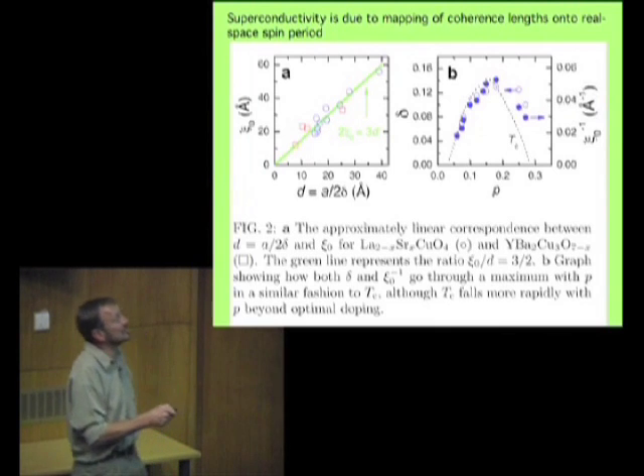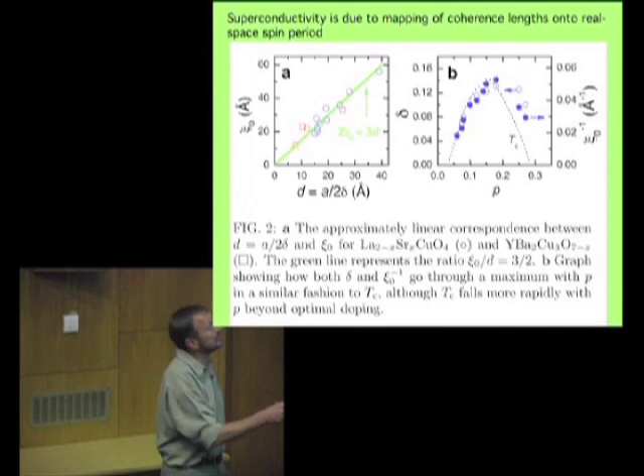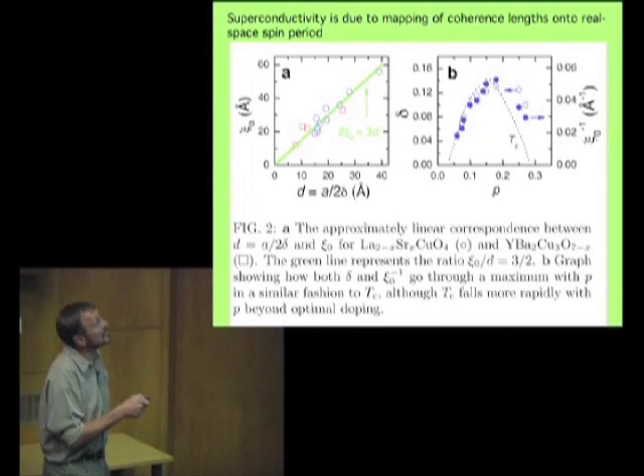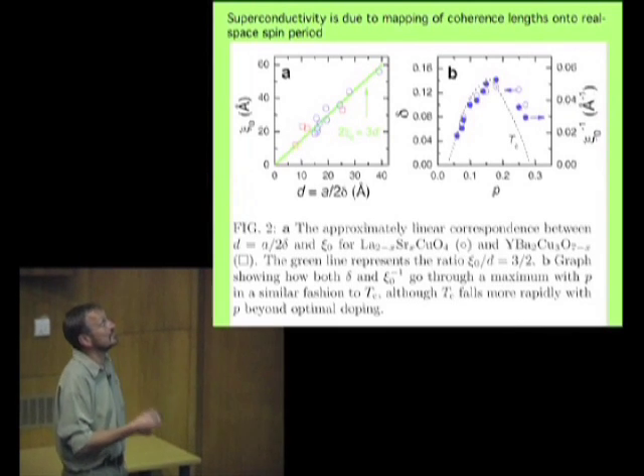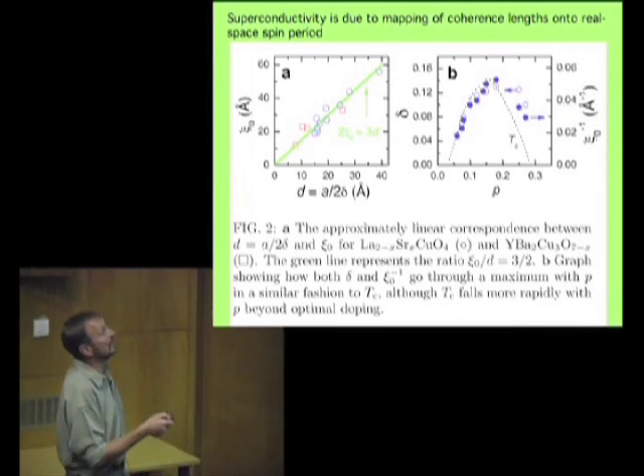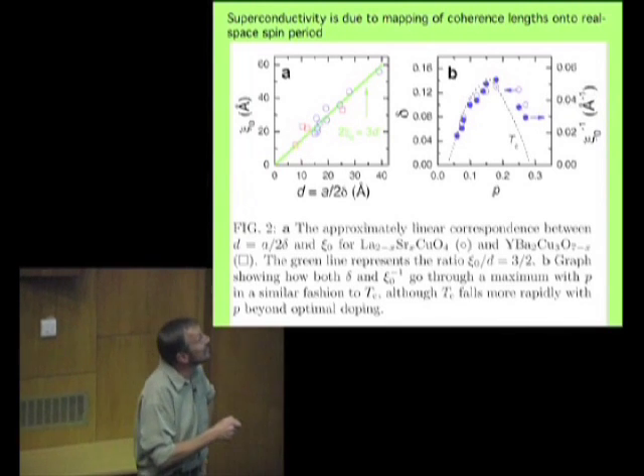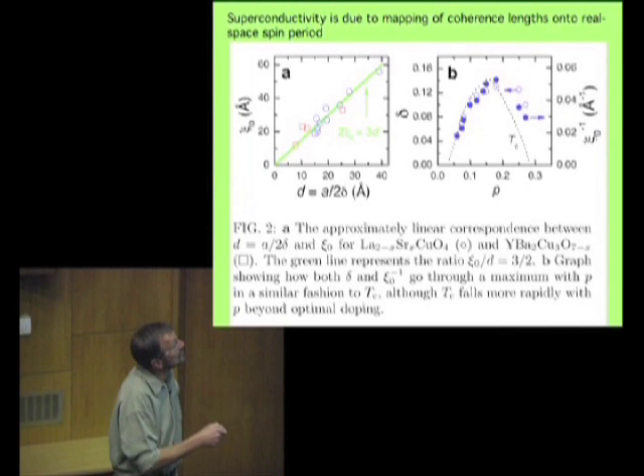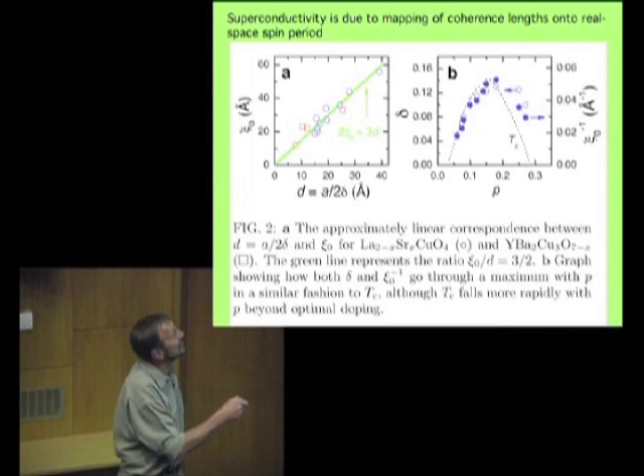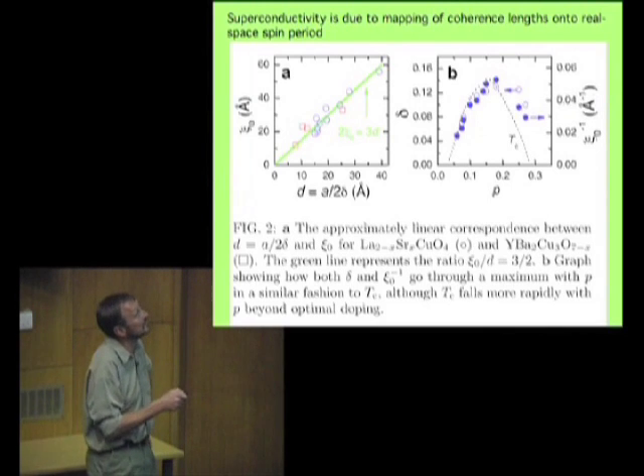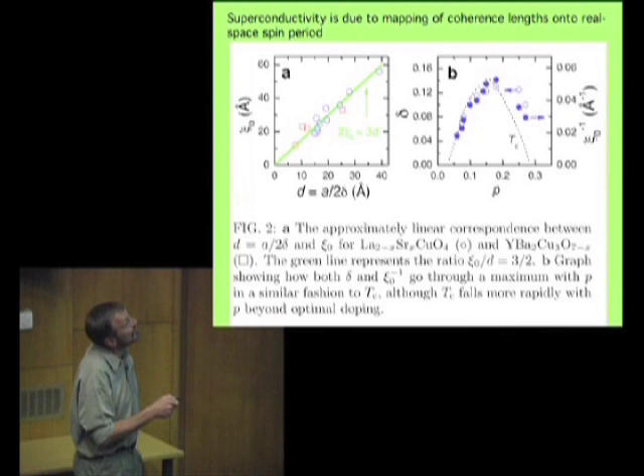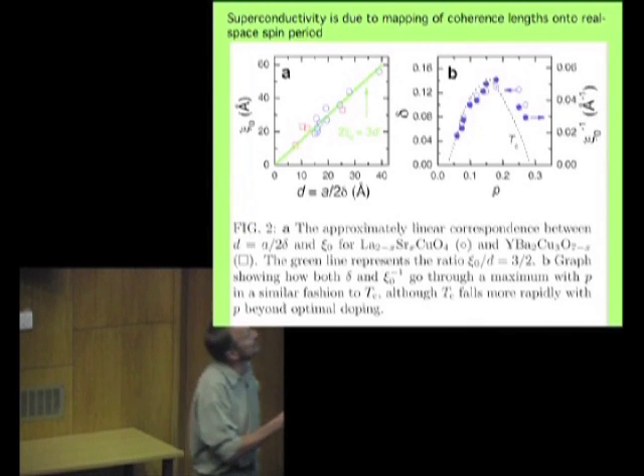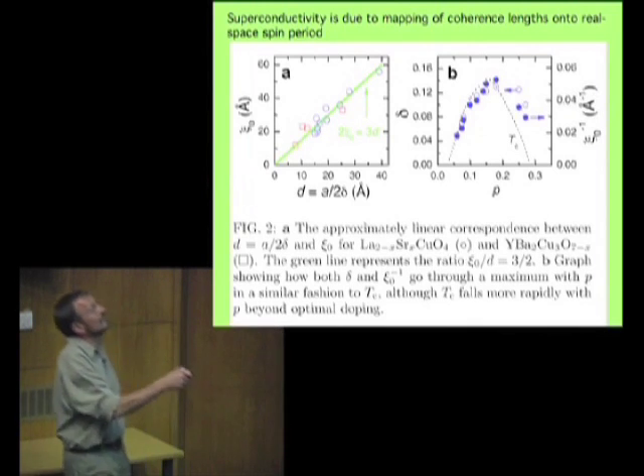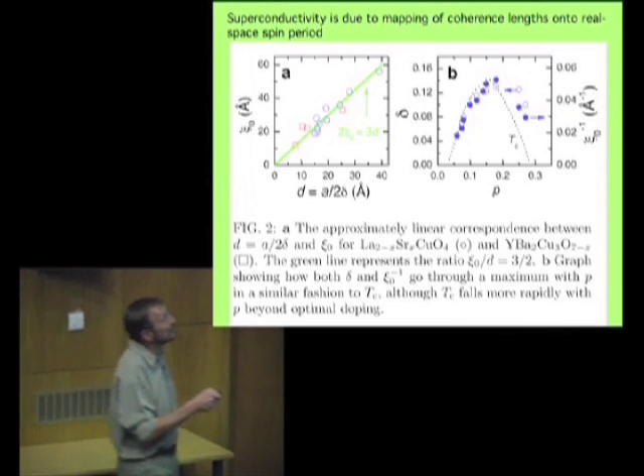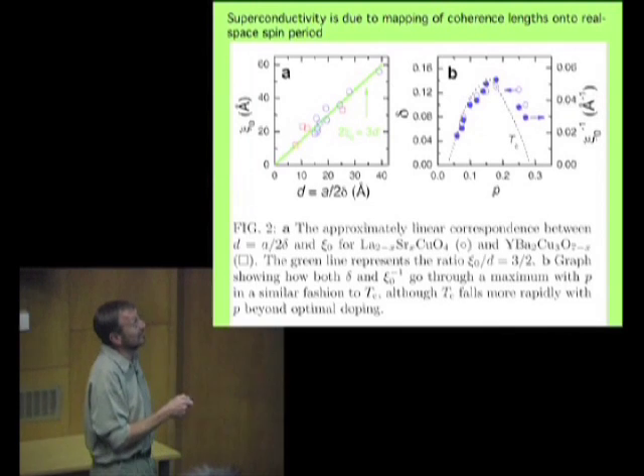Now this parameter d is just the lattice parameter divided by the delta that we measure from the neutron scattering data. So this is the theoretical expectation if there is a matching between the spin susceptibility and the Cooper pair wave function giving rise to the superconductivity. These are experimental data. Remember that this parameter is determined from neutron scattering, and this one from thermodynamic measurements. These are independent measurements of the two parameters. The square points are for YBCO, yttrium barium copper oxide. The round points are for LSCO, lanthanum strontium copper oxide. You can see that they all lie very close to this line, which is reasonably remarkable, I think.